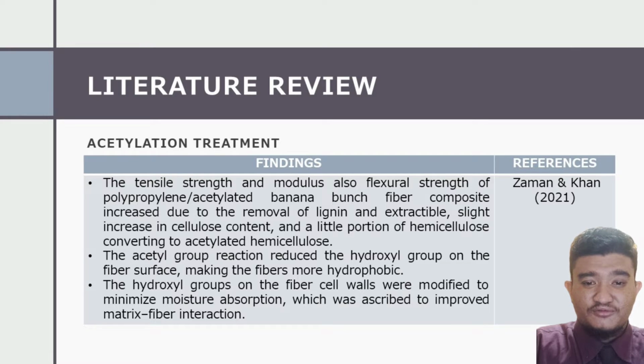Next, we move on to acetylation treatment. From the finding, the tensile strength and modulus, also flexural strength of polypropylene acetylated banana bunch fiber composite increased due to the removal of lignin and extractable, slight increase in cellulose content, and a little portion of hemicellulose converting to acetylated hemicellulose. The acetyl group reaction reduced the hydroxyl group on the fiber surface, making the fiber more hydrophobic.